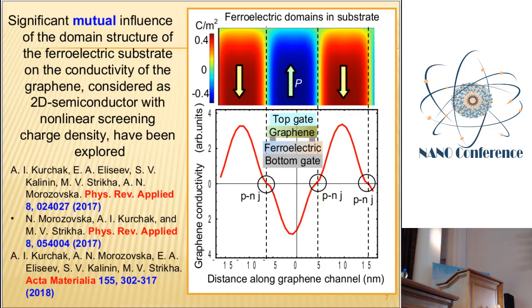A much more interesting situation is for a ferroelectric which is covered by a graphene layer. Graphene is a Fermi-Dirac 2D semiconductor, and in this case the screening in graphene is principally nonlinear, described by the well-known Dirac equation. And this nonlinear screening leads to a mutual influence of the domain structure of the substrate on the conductivity of the channel. As a result of these nonlinear interactions, p-n junctions are formed in graphene. Each p-n junction corresponds to a domain wall of the ferroelectric. And in principle, if we can control the amount of domain walls, their velocity and their formation, we can control the conductivity of the graphene channel, and this can be used in field effect transistors, for instance.